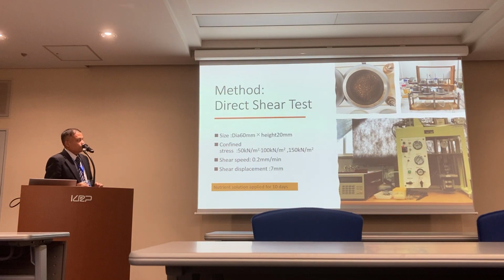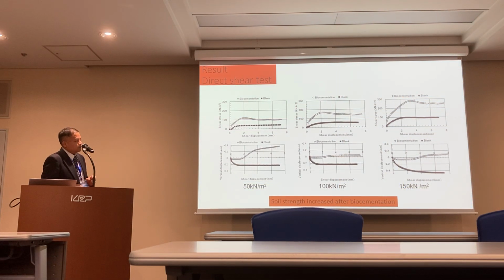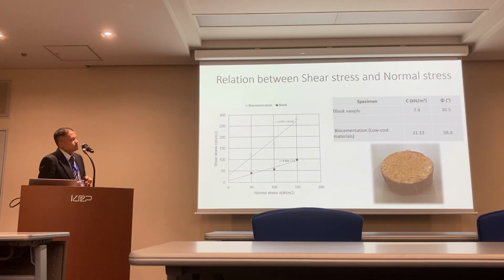Okay. Then we did a strength test by direct shear test, and we found that for the biocementation samples, the strength increased. If we look at the cohesion C and friction angle phi and the compressive strength, these also increased with the biocemented samples compared to the blank sample.